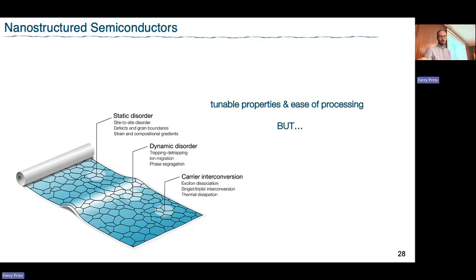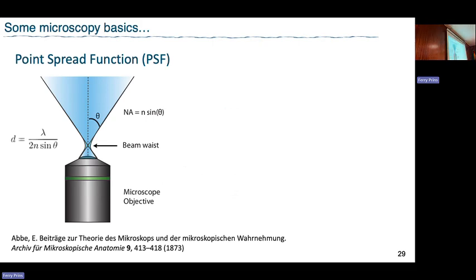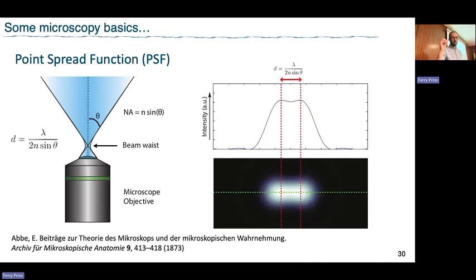But if we then use an optical microscope, we run into a very fundamental law, the diffraction limit, which tells us that my beam waist, no matter how expensive my objective is, is going to be at best around 250 nanometers if I work in the visible regime. So we're not going to be able to resolve anything below that 250 nanometers. Basically, your standard diffraction limit: where you have two fluorophores, you cannot distinguish one from the other if they are situated below that diffraction limit. And so 250 nanometers more or less is our hand-wavy limit. But our structure, if we have nanoparticles, is below that. So if we want to learn something about nanoscale transport, we need to play tricks.